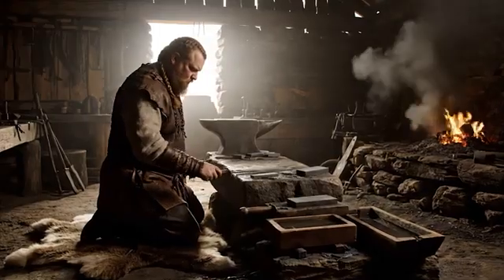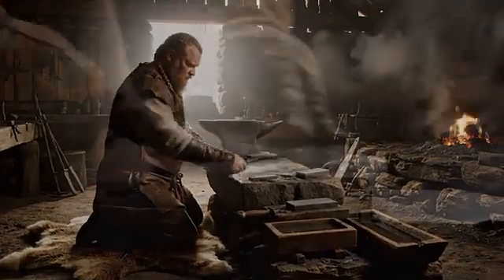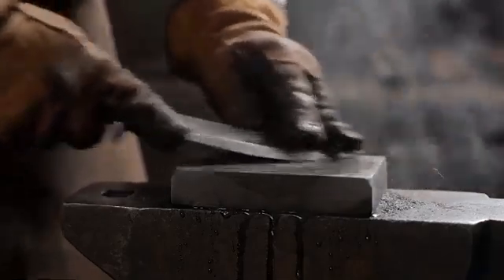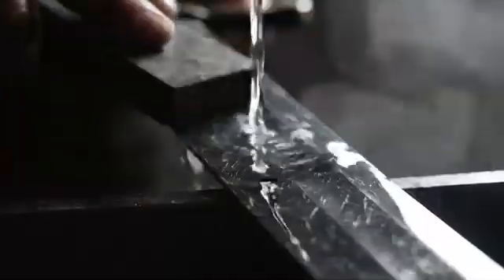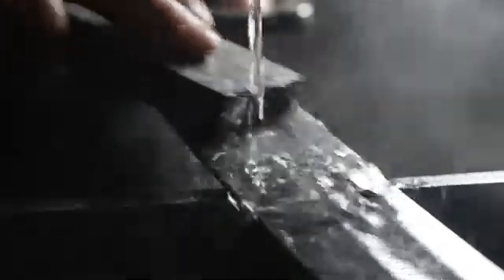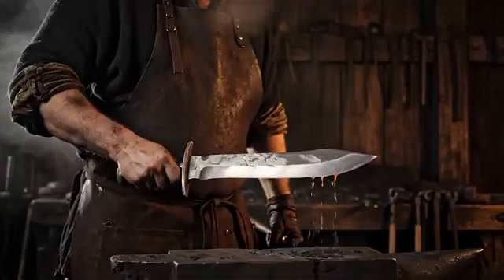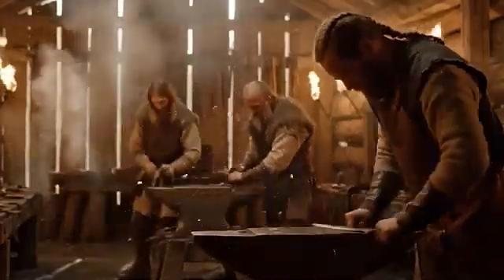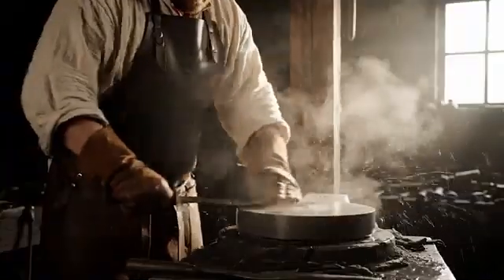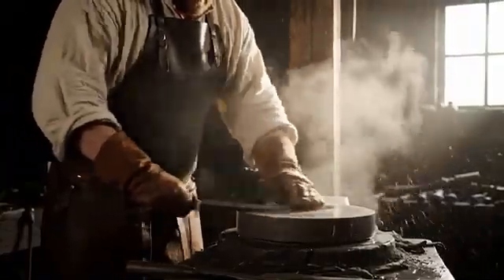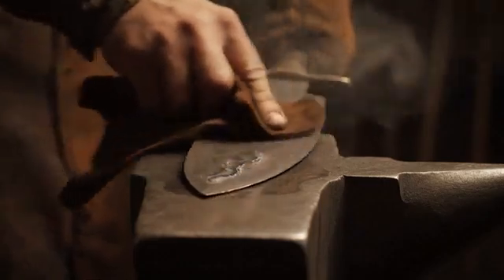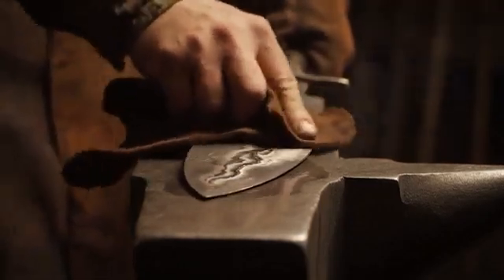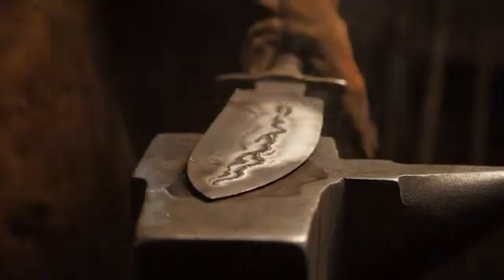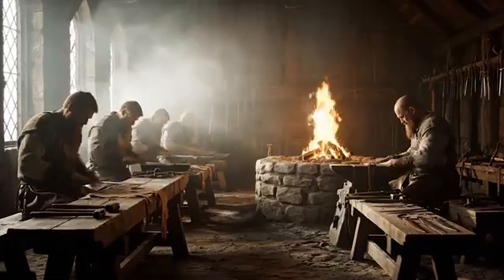The finished blade was still far from being called a sword. A long and painstaking finishing process began. First, the blade was carefully ground with abrasive stones of varying grit, moistened with water. Grinding removed traces of forging and hardening, leveled the surface, and formed perfectly smooth bevels to the blade. This process could take several days. It was during grinding that the hidden pattern began to appear on the surface of blades, made using pattern welding technology. Grinding was followed by polishing.